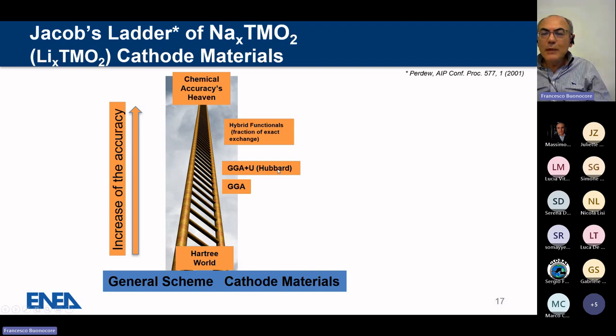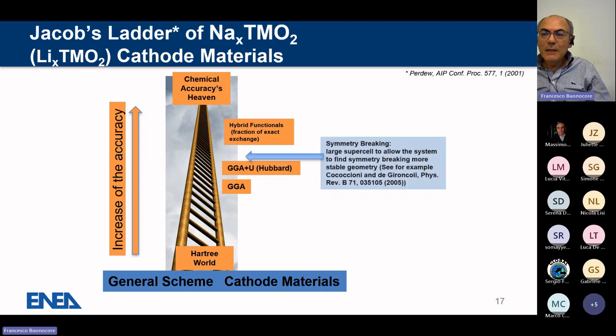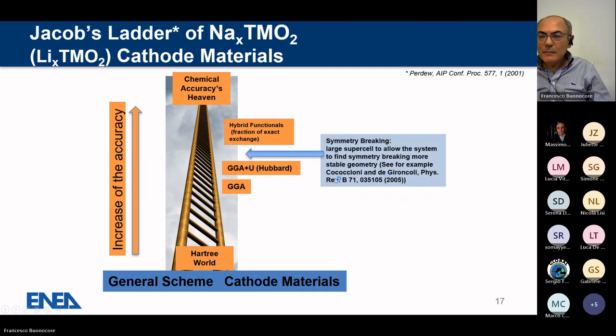Then we can introduce Hubbard corrections, and then you can use the hybrid functionals that are very expensive. Anyway, for a smaller system, for a smaller crystal with something like 30, 40 atoms, you can afford this kind of calculations. In the middle, we have also the symmetry breaking. When we model our system with a large supercell, you allow the system to relax, you can find the symmetry breaking that allows you to reach more stable geometries. In our approach, we combine the symmetry breaking approach with the Hubbard correction approach.